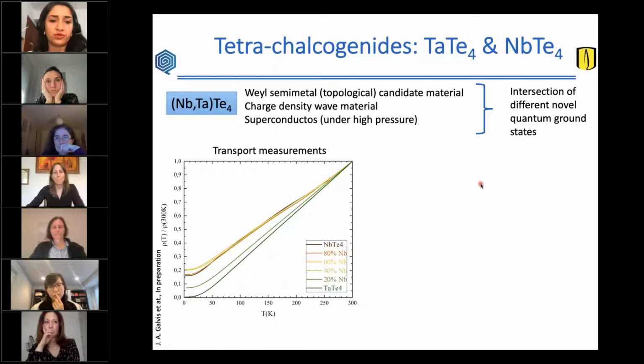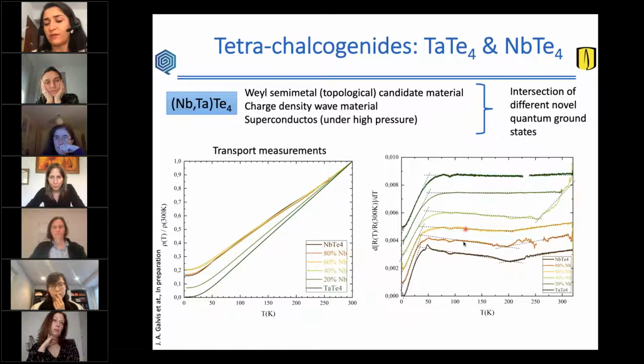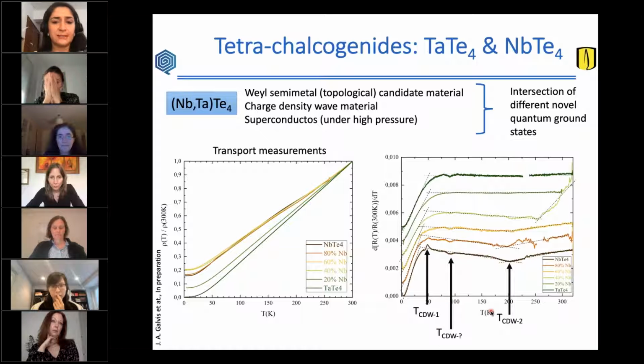So we have performed some transport measurements for the solid solution of niobium and tantalum tellurium 4, seeing not a very pronounced evolution in the electronic properties, but more pronounced evolution in features that we observe in these resistivity measurements. This is the derivative of this resistivity, which could indicate an evolution of different transitions to the charge density wave states. So we figured out that if we want to study the intersection of these novel ground states, we need a very careful and detailed understanding of the basic ground states that we have, for which this family of materials has been known, which is the charge density wave.